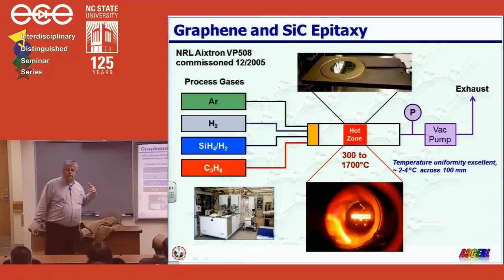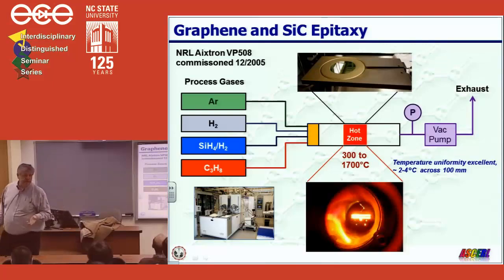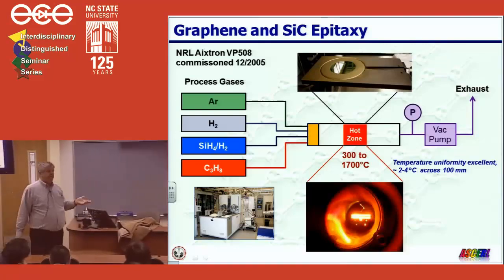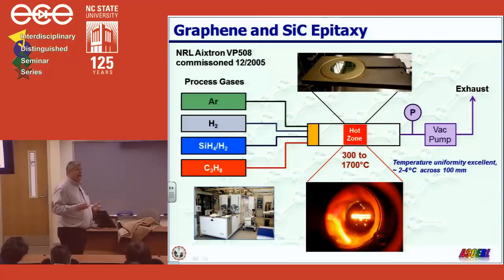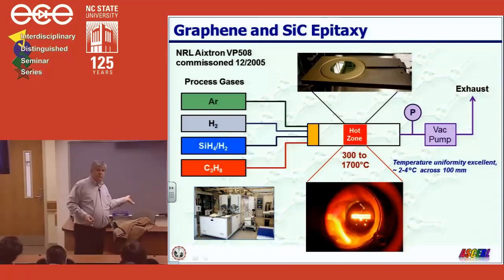Notice we use hydrogen. Hydrogen at 1600 degrees will etch just about every material known to man. And silicon carbide being a very hard material, it has polishing damage. So you need to etch it to remove the polishing damage. So we naturally etch our wafers before we put the graphene on them. And that also gives us an improvement of its properties.